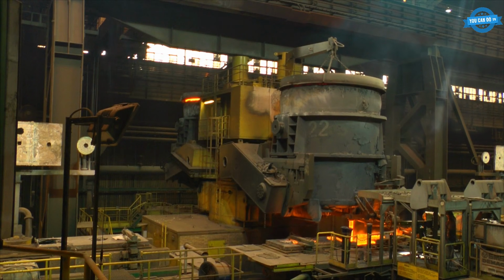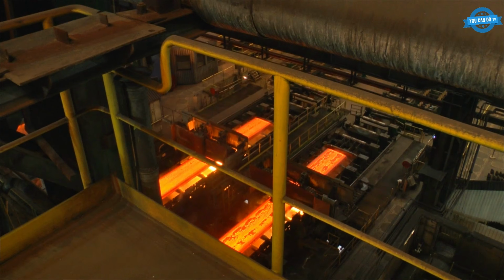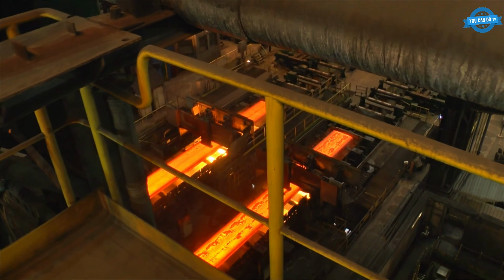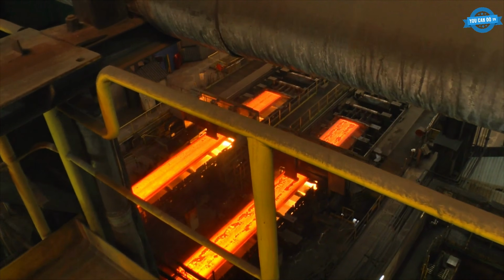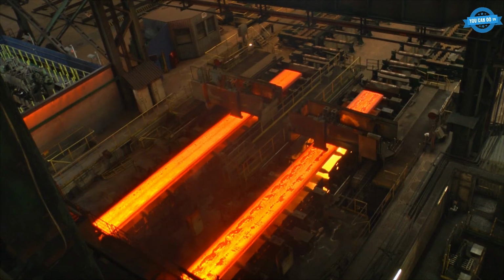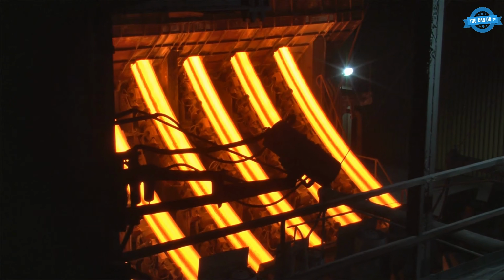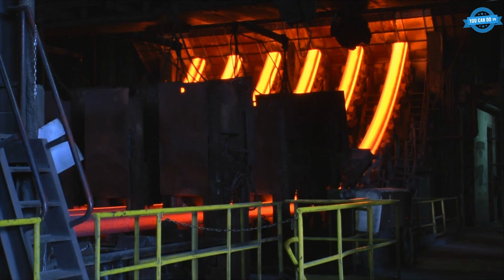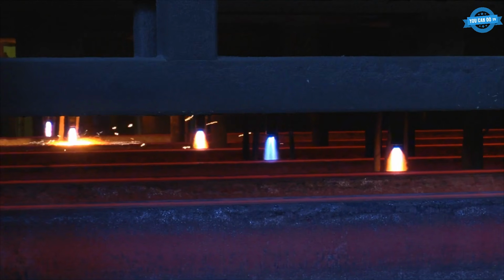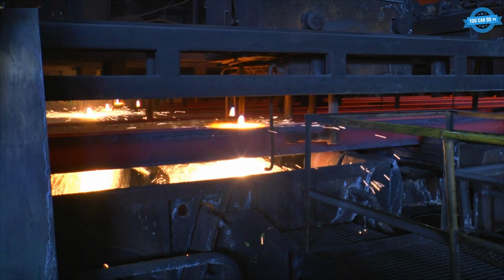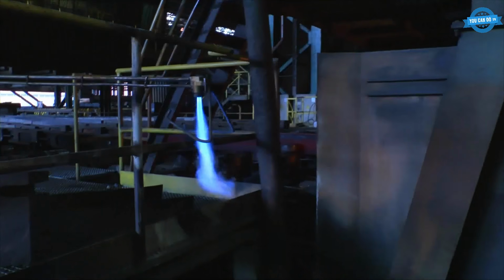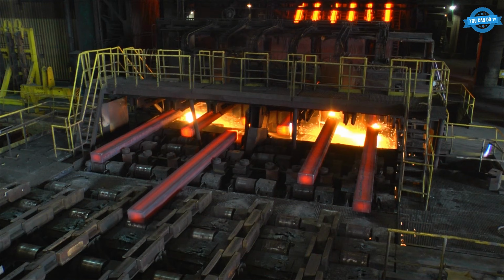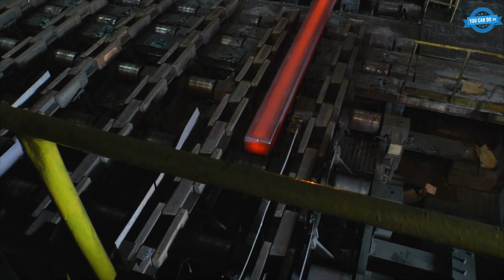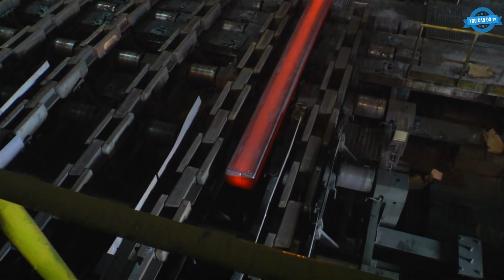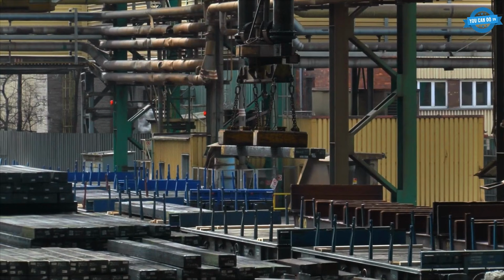3 enormous graphite electrodes descend from above, holding a fixed distance from the scrap pile, and an electric arc strikes between them and the metal. The whole furnace begins to hum with a low roar you can feel through the floor. Sparks shoot upward. The scrap starts sagging, then flowing, then puddling into a molten pool at the bottom. Slag rises as impurities separate. Oxygen lances inject through side ports to speed the reaction. Additives drop in from overhead chutes. The most recycled material on Earth is going through its next lap right in front of you.